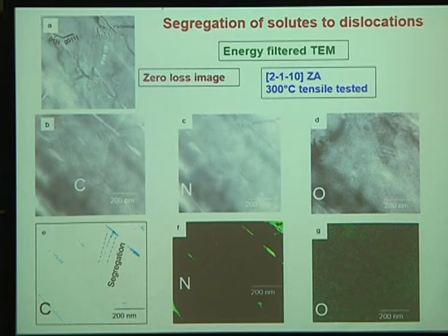In most cases, steels or nickel based superalloys contain solutes which are substitutional solutes or interstitial solutes. Both these solutes could give rise to serrated yielding. What is serrated yielding? As the dislocation comes and is stopped at obstacles, the solutes can come and form an atmosphere around them.